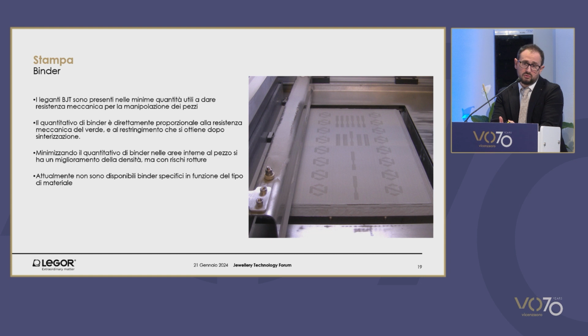Hypothetically, I can also work with areas devoid of binder, because maybe they're protected by an outer shell. And the advantage is increased densification. The number one enemy of good densification is the possible presence of binder that has not been eliminated, that did not evaporate, that did not evacuate. I have to guarantee a certain mechanical resistance, therefore, mechanical strength. So for the processing phases, I have to be on the safe side, and I need to guarantee, thanks to the binder, for the whole section of the item, a minimal strength.